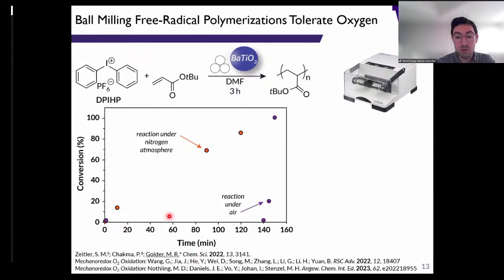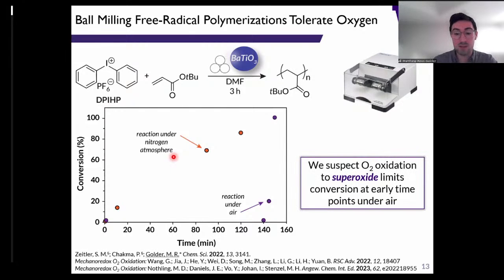You have this huge incubation period for just over 2 hours when we set these reactions up under air. And then we get really, really rapid conversion within the course of a few minutes. This is in stark contrast to the pseudo first order kinetics that we see under a nitrogen atmosphere in orange.